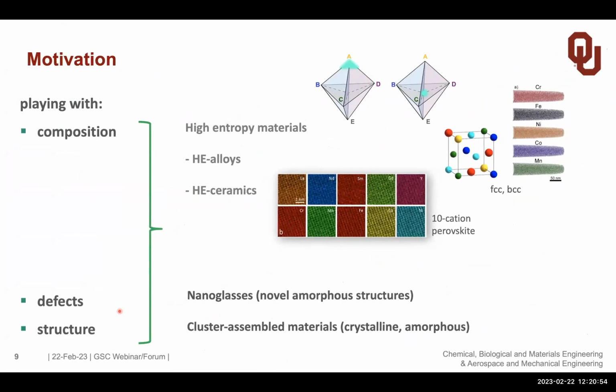Let me go a little bit into what I meant when I used this title of how we can use composition and defects, or disorder, in order to design materials. So this is one example where we play with a composition. And you know, we do that as material scientists a lot, because no material which we use is just a single element. There's almost no example of that. Even in a semiconductor where we use high purity, we still dope it in order to get the right performance. So we never have a pure element as a material which we are using. And so we can play with a composition.